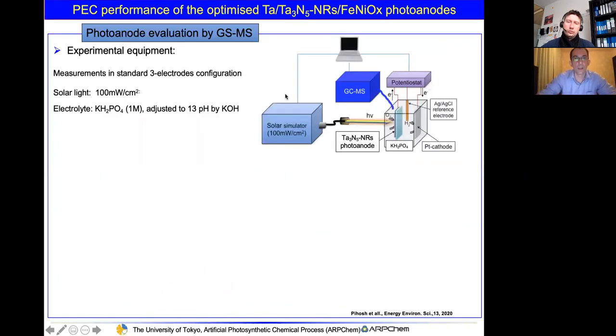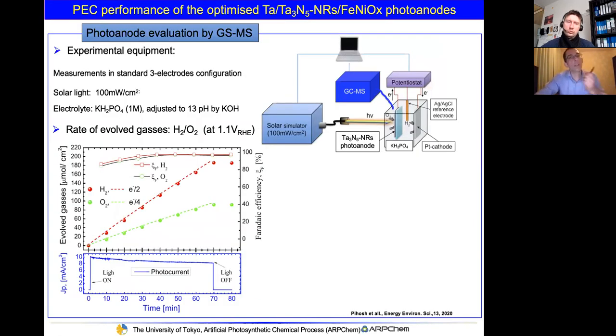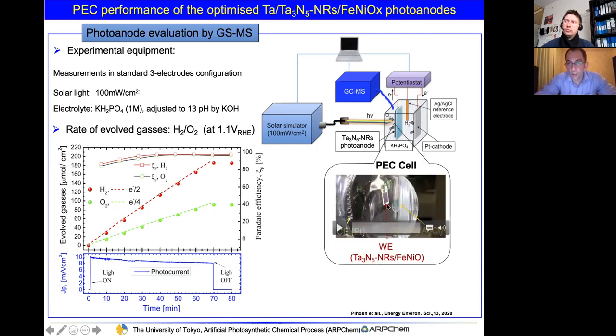Very nice. Okay, and then we evaluated the gas evolution rate in the same cell, but just connected the gas chromatograph here. And as you can see here, this is the video of the process of the generation. What we can see here is the photoanode material. This tiny bubble is the oxygen. This is our photoanode, this is the platinum counter electrode, and this is the reference electrode. Here, maybe you can see, or I don't know, if not, there is also tiny bubbling. So this is the hydrogen generation.